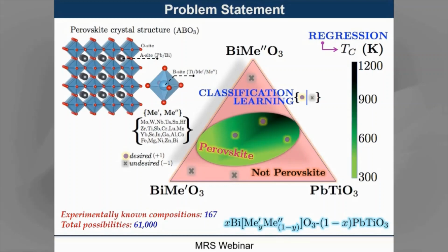And one of the intriguing aspects about this data collection process is that we were able to include experimental data from both successful and failed experiments, right? More specifically, a failed experiment here would denote that this specific stoichiometric composition either had secondary phases with substantial phase fraction or did not even result in a perovskite crystal structure. So this was necessary because in the future, we were much more interested in letting our machine learning models learn from failure and avoid recommending new materials that would not have a perovskite crystal structure.